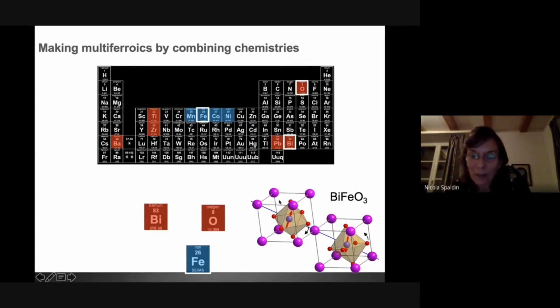For the experts, it has the perovskite structure. The iron ion is magnetic. It has a very large magnetic moment, 5 Bohr magnetons. It's coordinated octahedrally by oxygens. And at the corners of the unit cell here are bismuth ions. And the bismuth ions give the electric dipole because they have a stereochemically active lone pair.